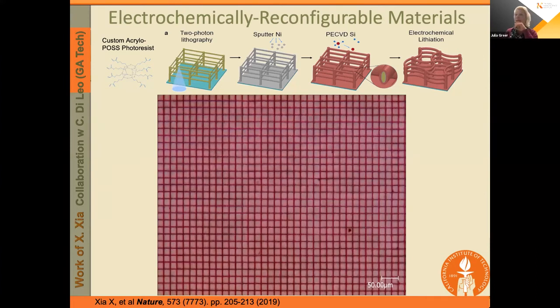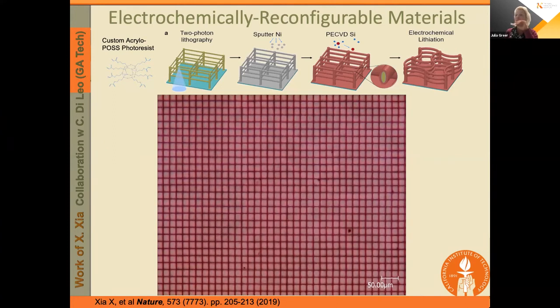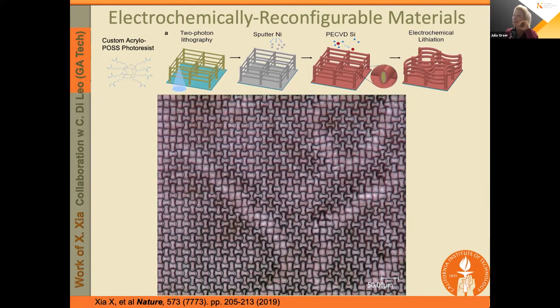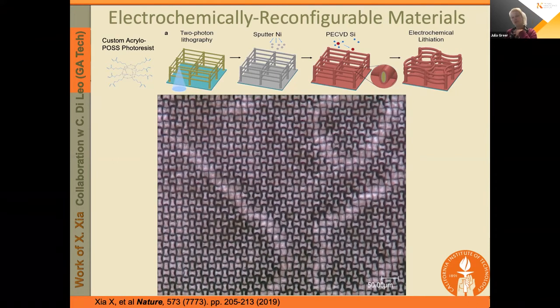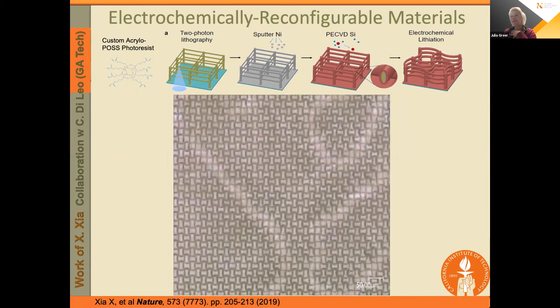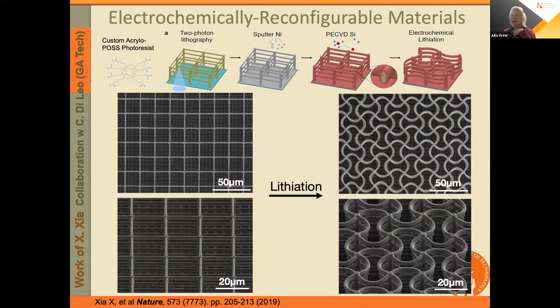And so watch what happens here. This is a top view of one of these microlattices as it's being lithiated. And what you can see is the formation of these patterns. Now, I'm a musician, so to me, they look like violins, but some may say that these are sinusoidal patterns. So I'm showing you the top view as well as the tilted side view. And you can see that these beams are able to alleviate the stress buildup in response to lithiation by buckling out of plane and in plane. And you can see this buckling is coordinated.